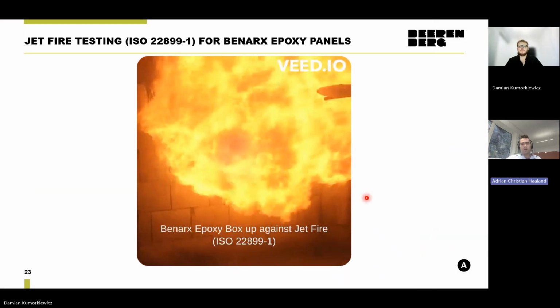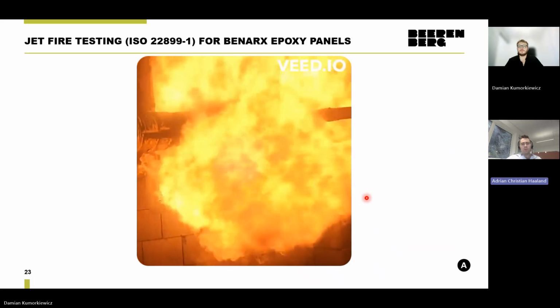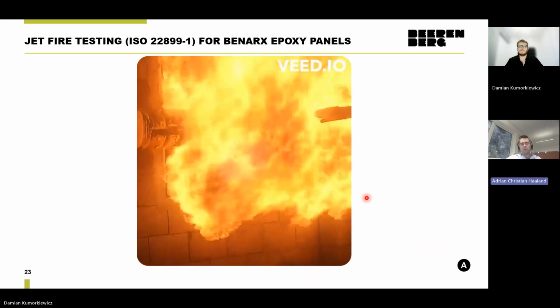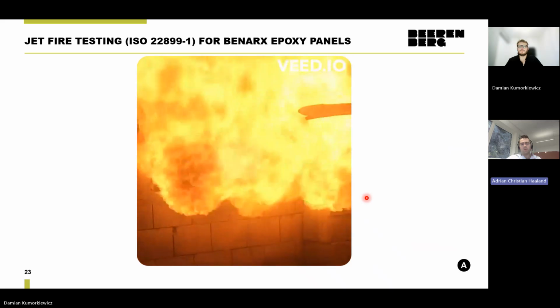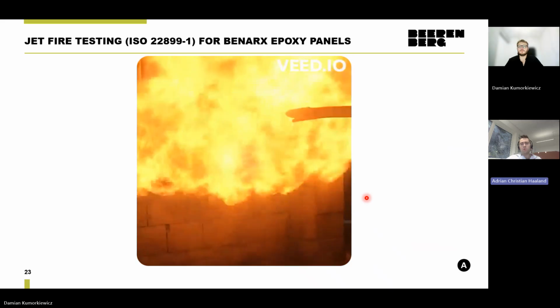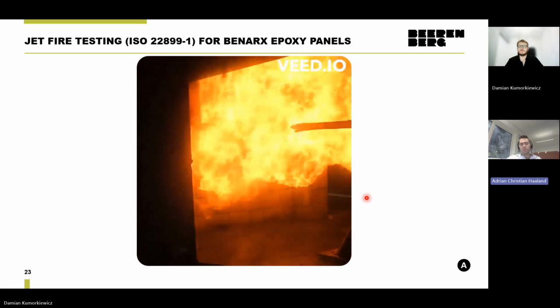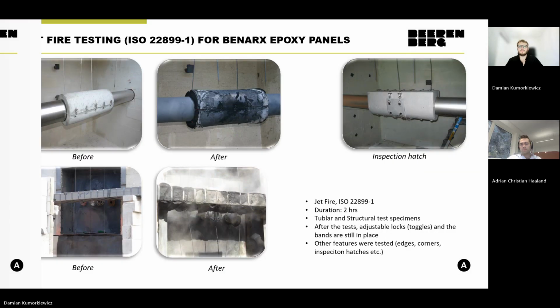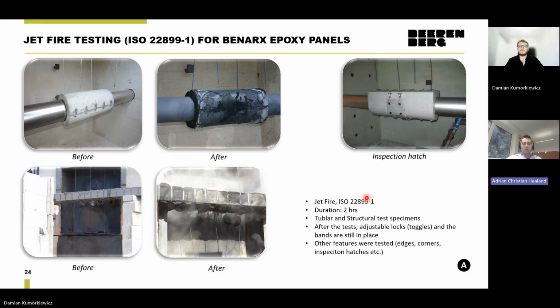And this is how it looks. This is for a piping test, and you can see the sheer velocity and turbulence and erosion going on. The thing about jet fire is that it's not only the temperature, like the heat radiation, it's also the turbulent stream of gases continually eroding and sanding away at the PFP. When we do testing, we also encompass different complexities, like in this case, an inspection hatch.